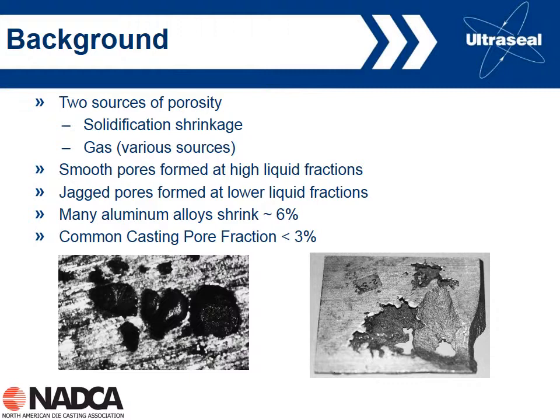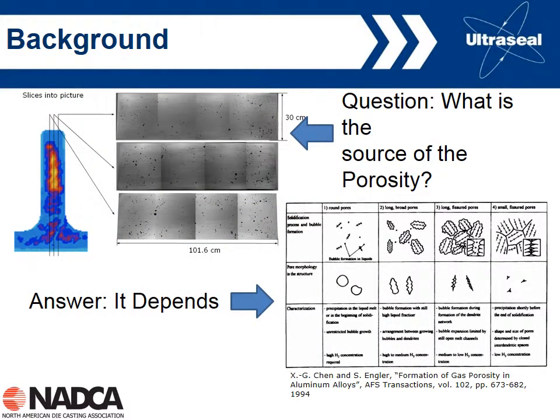And so we also discussed these 2 types of porosity in a little bit more detail. The picture here on the left, we have these smooth pores, and the picture on the right, we have these rough, jagged pores. And we talked a little bit about the physics of the pore formation. The smooth pores tend to be associated with higher liquid fraction. They tend to form early in the solidification process when it's mostly liquid around, so there's still a high liquid fraction. Often this is associated with entrapped gas, but not always. And then the jagged pores, the ones on the right, tend to form at lower liquid fractions.